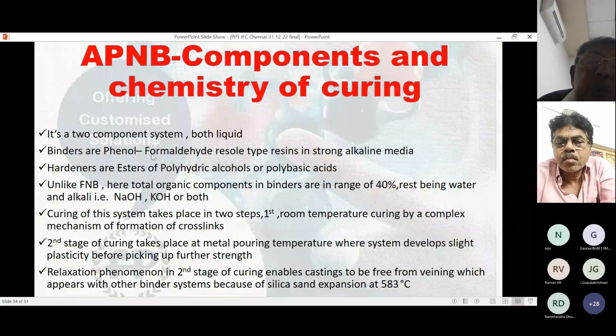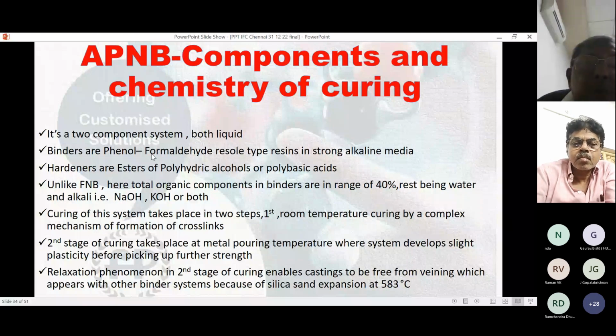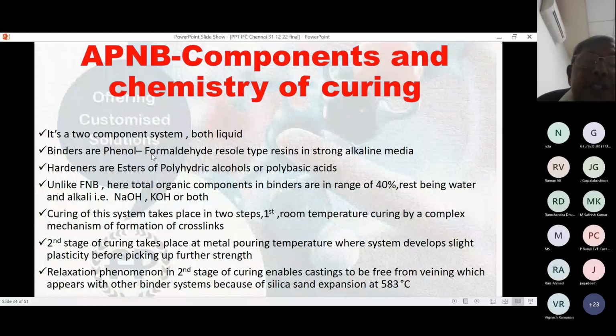Curing of this system takes place in two steps. First, room temperature curing by a complex mechanism of formation of crosslinks. So this is precisely the dry strength. And the second stage of curing takes place at metal pouring temperature, where the system develops slight plasticity before picking up further strength. Relaxation phenomena in the second stage of curing enable castings to be free from veining, which appears with other binder systems because of silica sand expansion at 583 degrees centigrade.